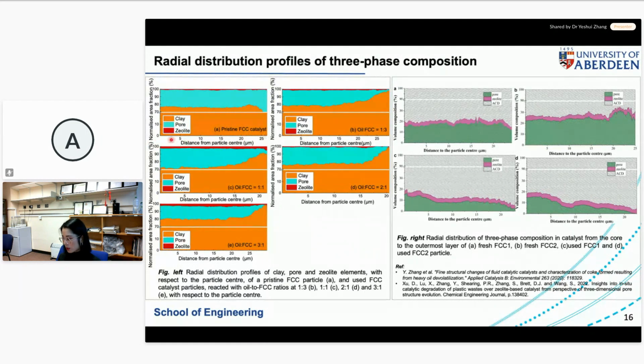The x-axis here, 0 indicates the center of the FCC catalyst particle, and 25 is the edge of the particle. What we can see is that the main structure of this catalyst, the clay, is almost homogeneous throughout the particle, but at the surface you can see more pores. I think that makes sense because this catalyst is pristine and fresh. We haven't used it at all, so there are more open pores at the surface. Meanwhile, the red area in this figure is the homogeneous distribution of the zeolite throughout this particle. The rest of the figures here are the different degraded stages of this catalyst.